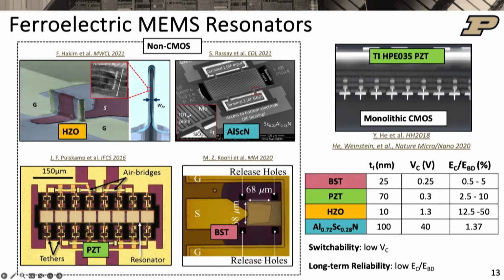CMOS wants to go really, really thin, so you can get very low voltage switching, which means low power memory switching, right? But in MEMS, we actually want a large volume of our vibrational mode to be piezoelectric, so I get better transduction efficiency. But when you go thicker on these ferroelectric films, they lose their ferroelectric properties. And so there's this interesting material optimization that has to happen.